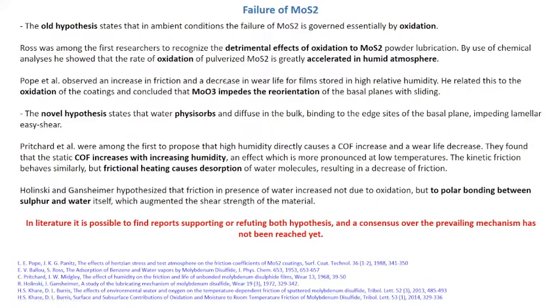But other researchers in the middle of the 1990s proposed another solution related to these aspects, because they observed that the coefficient of friction slightly decreases when increasing the temperature of the substrate. And they explain this experimental evidence by supposing that water molecules can physisorb and diffuse in the bulk, sticking to the edge of the basal planes, and so impeding the lamellar easy shear.